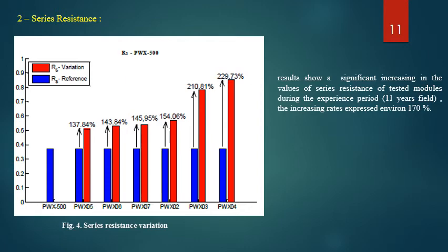The RS of the PV module arises from the resistance in solder joints, cell metallization, and the cell interconnect busbar. The increase of RS reduces the voltage produced by the photovoltaic panel in the hot desert climate conditions, such as the heat combined with high UV irradiation. The thermal stress leads to fatigue cracks at the solar interconnection that increase the series resistance of the tested PV module. This results in an overall drop in the power generated by a PV module. The results show that significant variation in series resistance mainly contributes to early degradation and the power drop of polycrystalline silicon in desert climate.